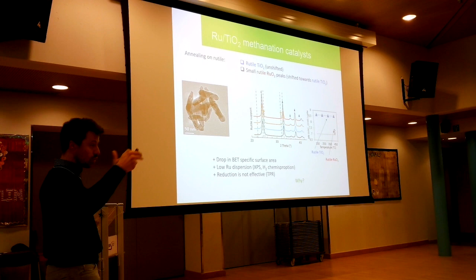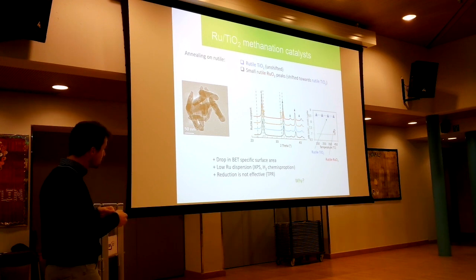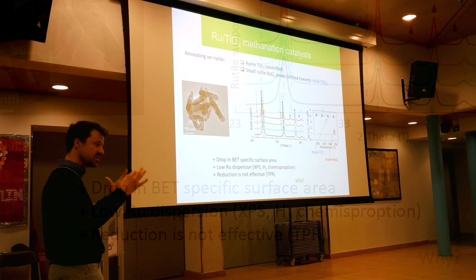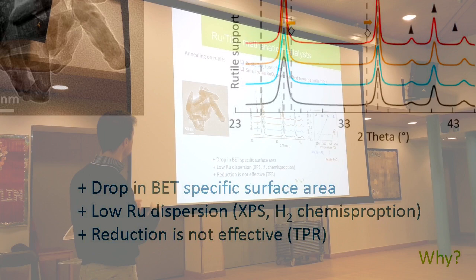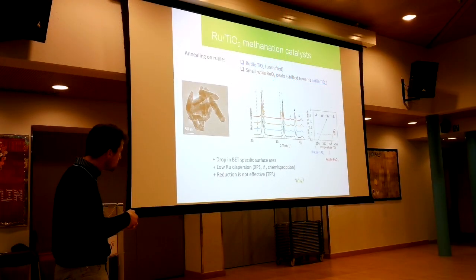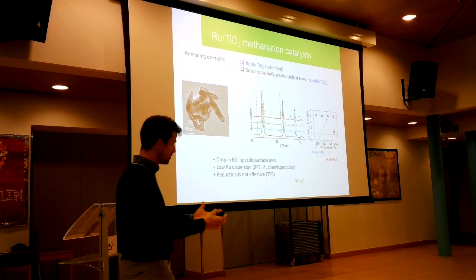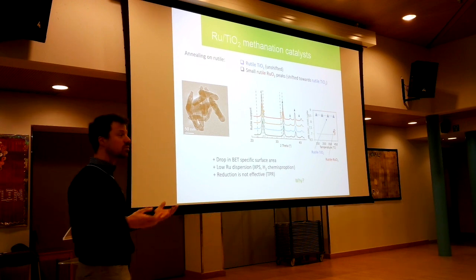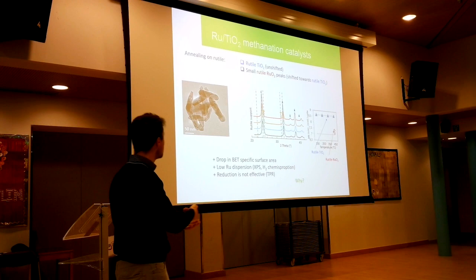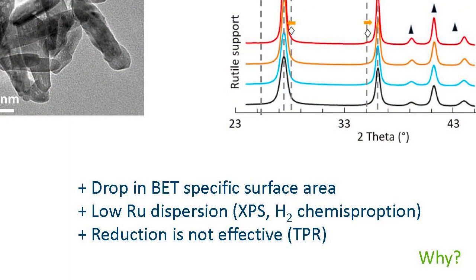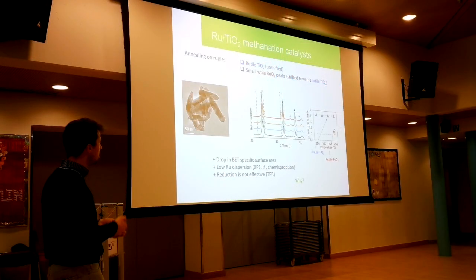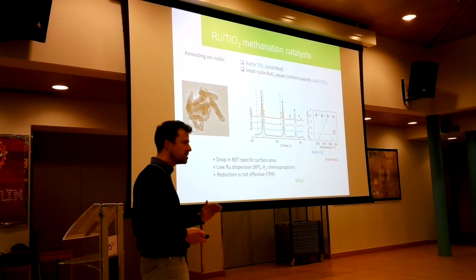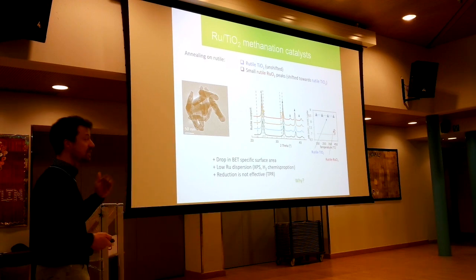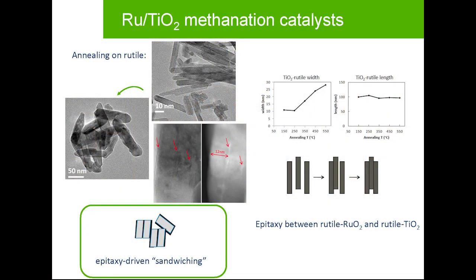I don't have the time to go into all the characterizations, but as a summary, I can also say that the specific surface area of the catalyst decreased a lot when we did the annealing, the calcination. Also, when we analyzed the surface composition, so the accessibility of the ruthenium, we realized that the amount of ruthenium that was actually accessible to us, to our probes, by XPS or by hydrogen chemisorption, was low, which was surprising. And also, when we tried to reduce the ruthenia, we realized that only part of the ruthenia was actually accessible for the reduction. So what happened?